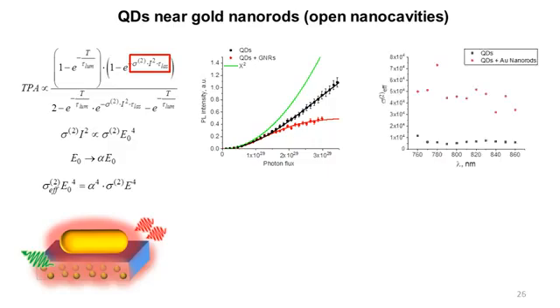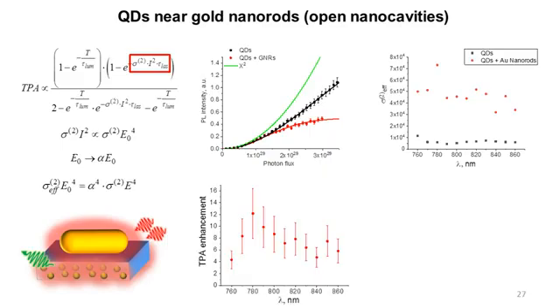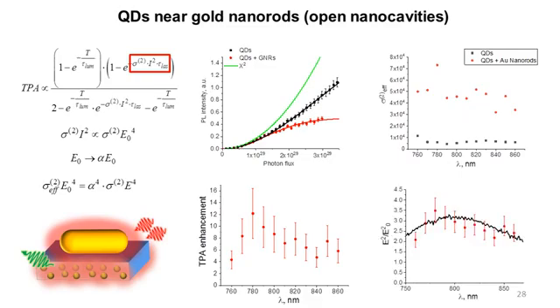Thus, we have extracted the two-photon absorption cross-sections from these dependencies at different excitation wavelengths. One can see that the effective cross-sections near the gold nanorods were much higher than the simple cross-sections of quantum dots. Using these values, we have calculated the enhancement of the two-photon absorption, which was up to 12. One can see that the calculated increase of the excitation intensity follows the plasmon spectrum of the gold nanorods, which proves that this enhancement is the result of the plasmon-induced effect.